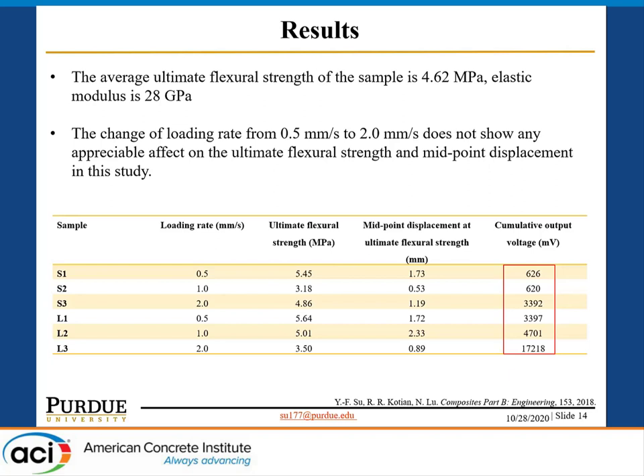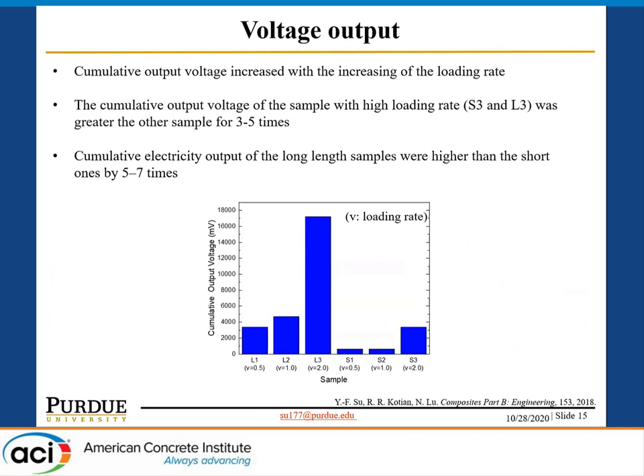But it's worth noting that we also recorded the cumulative output voltage during the testing. This slide shows the samples with different configurations and the cumulative output voltage. We can see that the cumulative output voltage increased with the increase of the loading rate, and the sample with a high loading rate has a greater voltage than other samples by 3 to 5 times, and the long length sample has a higher result than the short one.